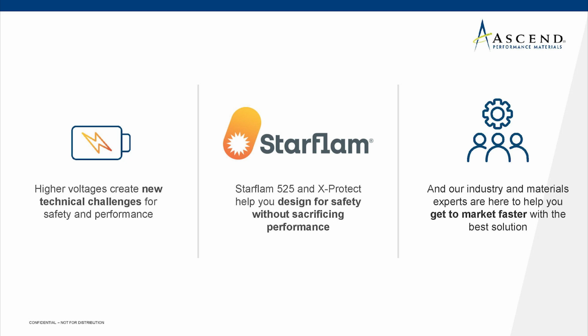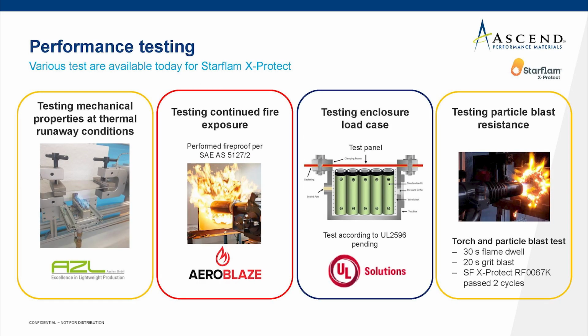And then Kai, how does X-Protect behave under a particle blast? On one of the slides of the presentation, if you click back to that page, we already talk about that particle blast. We ran particle blast and flame dwell in a slightly different cycle than you might be used to from other test laboratories. We used 30 seconds flame dwell and 20 seconds grit blast. In this exposure, we are passing 2 entire cycles with X-Protect injection molded material in a 3 millimeter thickness substrate.